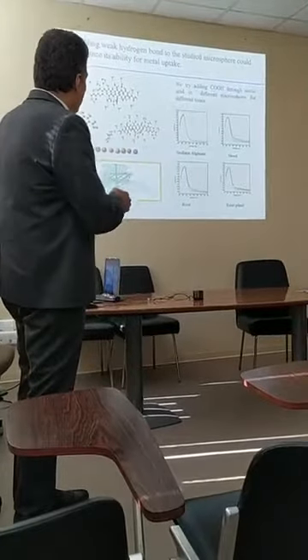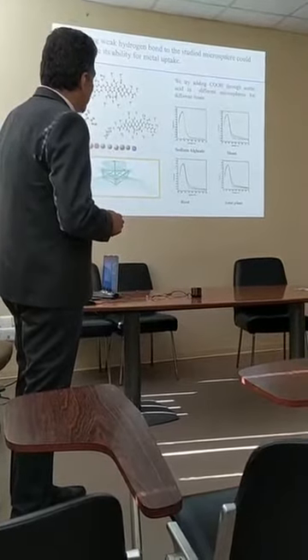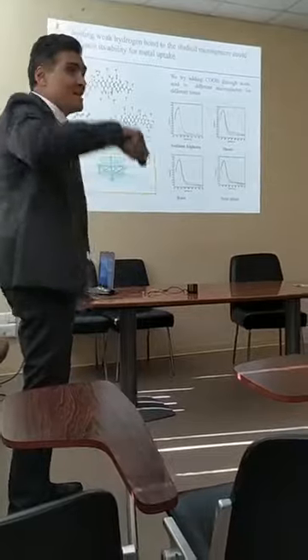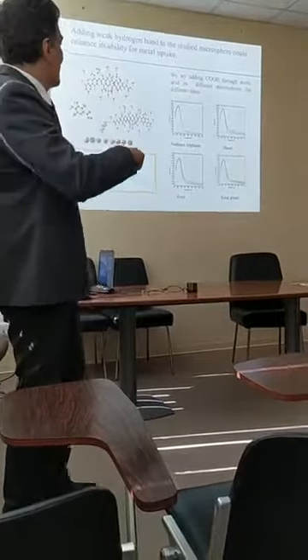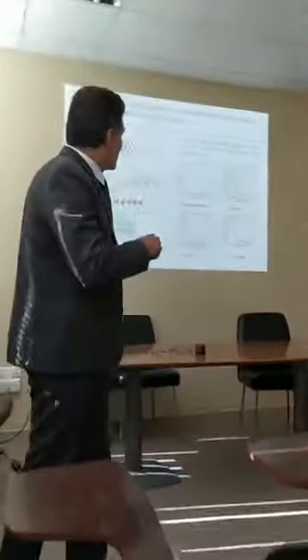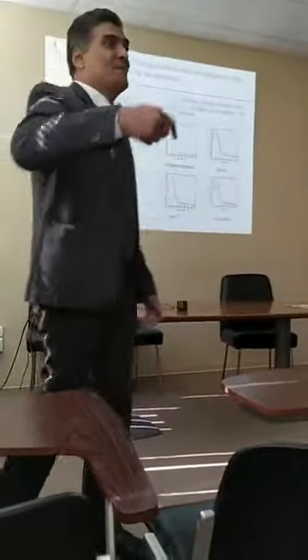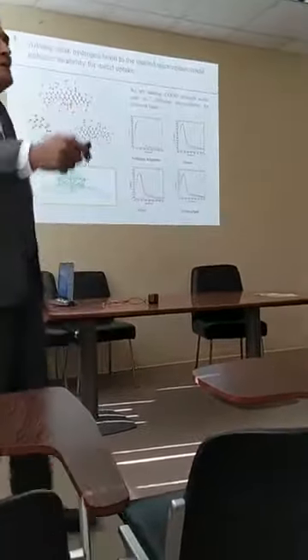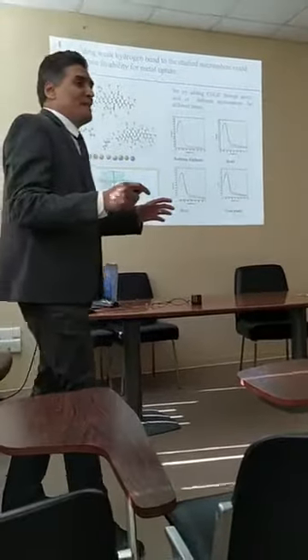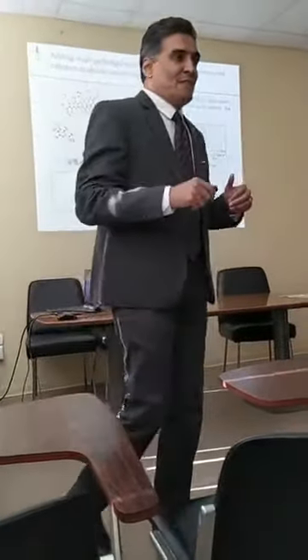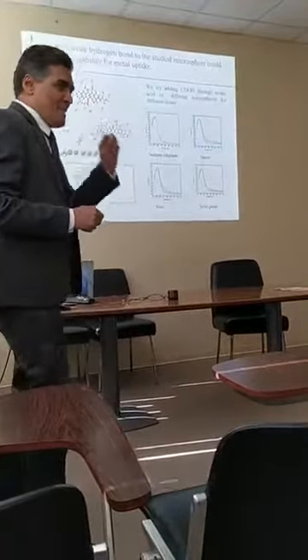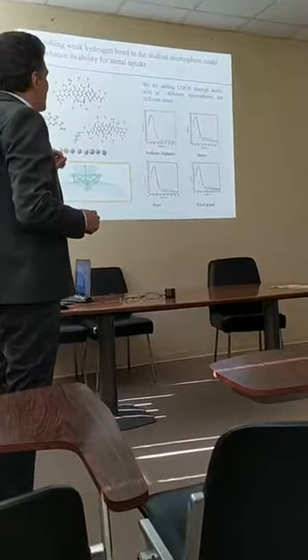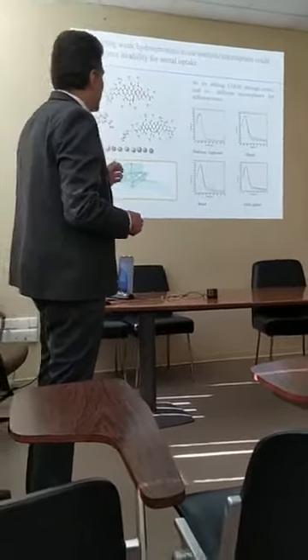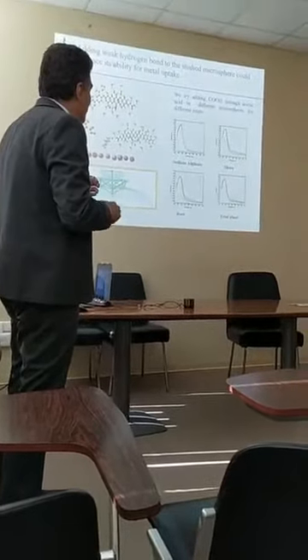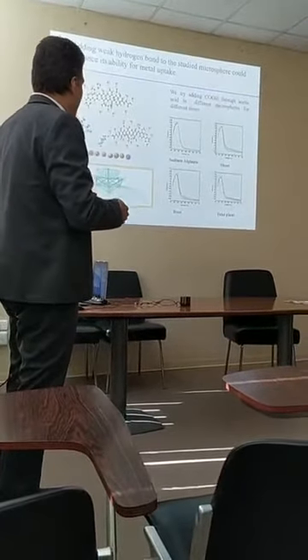So we took sodium alginate and did some treatment, a dipping experiment, I did this in Egypt, with the carboxyl group. It seems that if you treat the sodium alginate for a short time, it gets some kind of saturation with acetic acid. We got free carboxyl groups, and then we increased the number of hydrogen bonds. In this sense, we put this functional group on the surface itself.